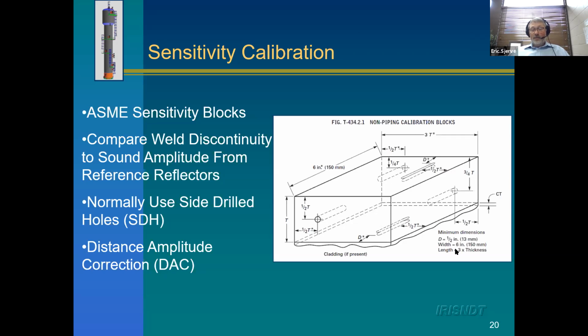And then a distance amplitude correction curve. As that sound goes farther and farther into a material, it attenuates and it spreads out. So we have to do that sensitivity calibration at different depths. So we get the same sensitivity close to the probe as we would far away from the probe. And once we've done those two parts of the calibration, the ultrasonic system is calibrated and we can do the inspection. And you should always see on any report that does any type of ultrasonic inspection, there has to be information and description about how the calibration was done.